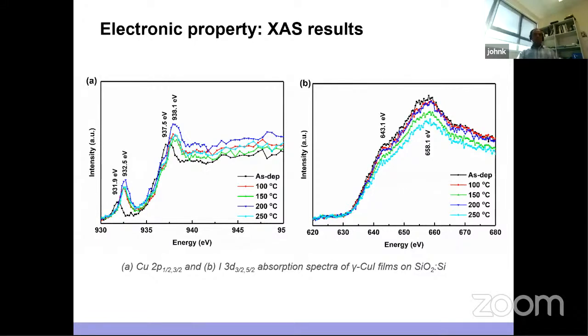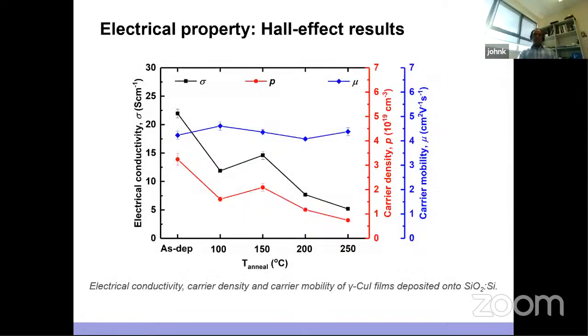So we looked more closely at the electrical properties, because that's what matters at the end of the day. As you can see, this gives you a nice overview of conductivity, carrier concentrations and mobilities. You can see the conductivity decreases after annealing. This is a very low temperature annealing. The reason we operate at low temperature is that it's the maximum temperature you can expect from sunlight hitting the glass window, depending on focus. So we are really keen to keep to really low temperatures to see how we can have a high power factor. The conductivity decreases due to the hole density decreasing from the copper vacancies.